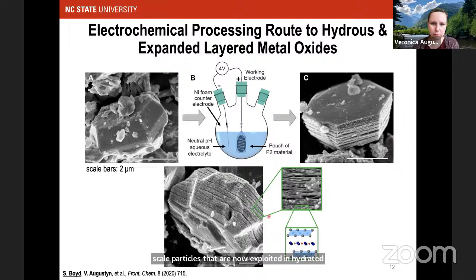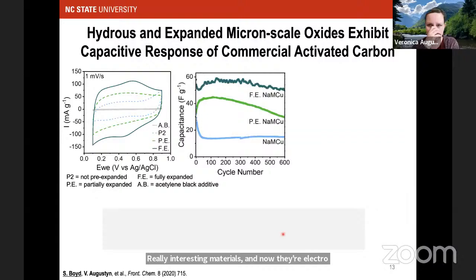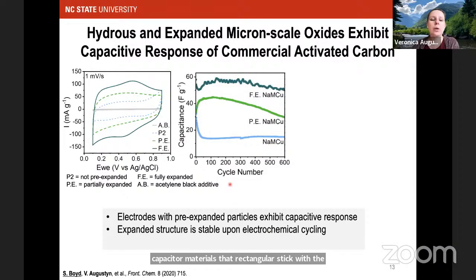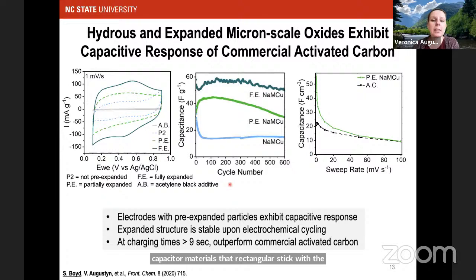Here's another picture of what that looks like. Really interesting materials. And now their electrochemistry is totally different. They behave exactly like capacitor materials, that rectangular cyclic voltammogram. The capacitive response actually is very similar to an activated carbon electrode, a state-of-the-art commercial activated carbon electrode that has 1,000 meters squared per gram surface area. The cycling stability is significantly improved.